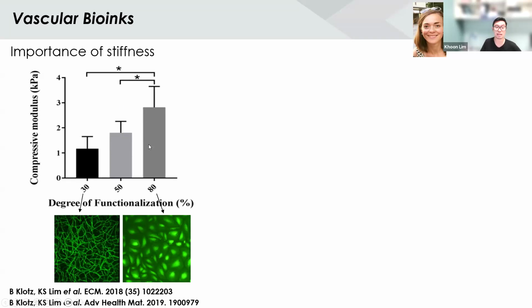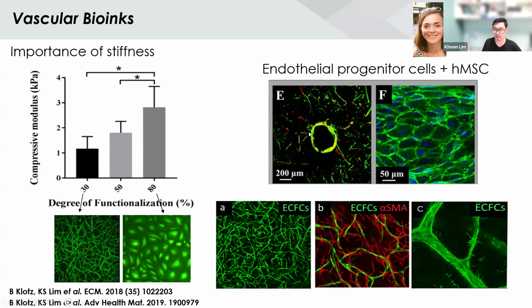If you increase the stiffness by a bit, not by a lot in this case, so 1 kilopascal to 3 kilopascal, the cells no longer form a microcapillary and they start forming an endothelium. So the vascular cells are very, very sensitive to the mechanics of the bioinks that we are presenting to them. And then by knowing that, we can start making constructs like this, where you have a channel where you can seed cells and they will form an endothelium within them. And then you can see in the surrounding bulk, we want the endothelium to be connected to microcapillaries.